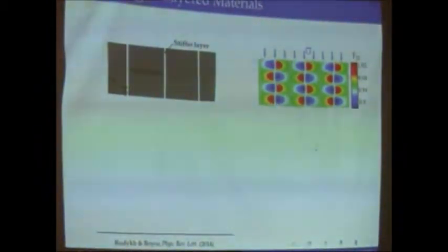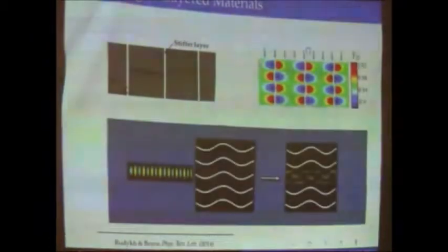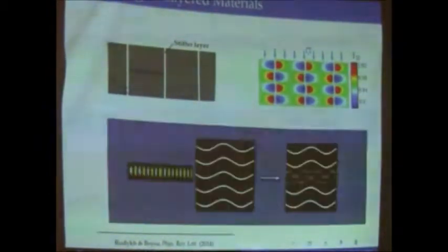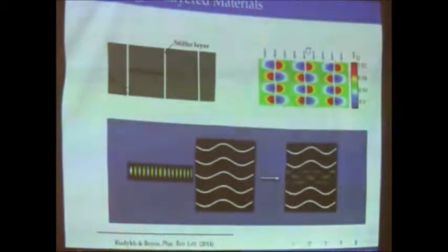Going back to the example of wave propagation in a homogeneous material, in these different regions the wave would feel a different material. So you create in a way a more complicated composite material. The material to begin with was very simple, just a laminate, and then the combination of the geometry change and the change of the local properties of the material gives rise to these band gaps in this situation.